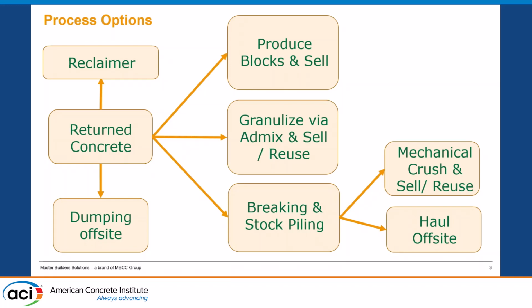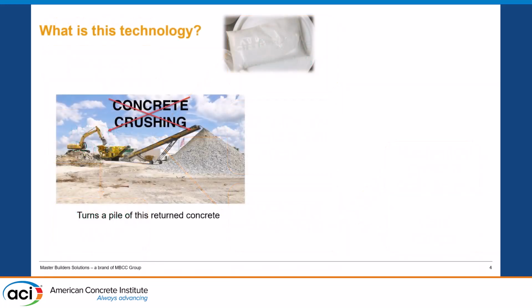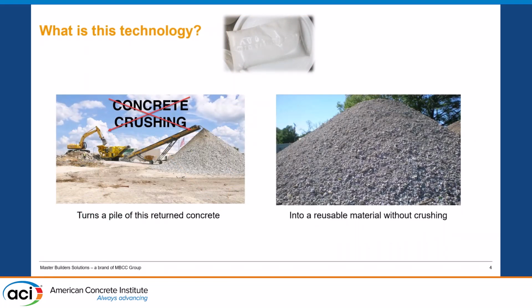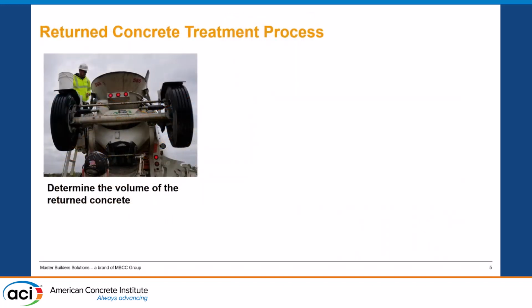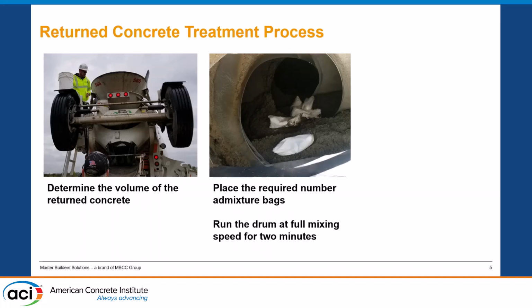So let's go and talk a little bit more about this technology, about how to transform plastic concrete into recycled aggregates. The technology consists of 3 different steps. First, when the returned concrete gets back on site, the total volume of returned concrete inside the truck needs to be estimated or determined. Then bags of this particular admixture are added to the truck, and the drum has to be mixed for about 2 minutes. This is a very fast-acting polymer, and in a matter usually of 60 seconds to, let's say, 90 seconds, you can already hear the different sound inside the concrete truck, from the traditional swooshing of more plastic concrete to the rattling of the aggregates being formed.